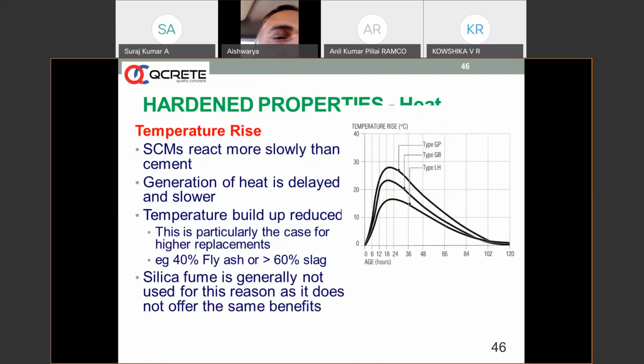One of the other significant contributions of SCMs in modern day construction is when we are constructing big rafts, where thousands of cubic meters of concrete are being poured, and the thickness of a raft may be more than 1 meter. Here, temperature rise over time becomes a significant factor. We have to measure the temperature at the core of the concrete and the surface of the concrete, and if the temperature differential is more than 15 degrees, then thermal cracks will occur. To avoid that, the only possibilities that concrete technologists and scientists have found are the usage of supplementary cementitious materials and certain other methods like insulating the concrete, and also using cold water, ice, etc. to keep the concrete cooler.